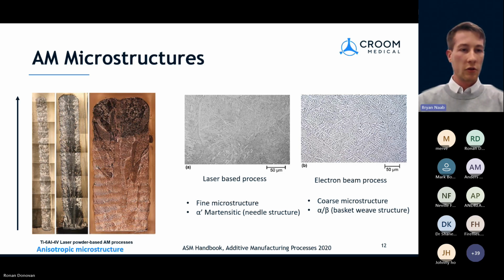Additive manufactured microstructures are very much directionally aligned with the build direction due to the flow of heat. If we compare a laser-based process microstructure to an electron beam-based microstructure, we see that the electron beam microstructure is coarser, so the grains are larger due to that hot chamber process, which also creates formation of secondary phases, such as the beta phase, whereas in laser-based processes, we generally have an as-built martensitic phase, which has implications for strength and ductility.